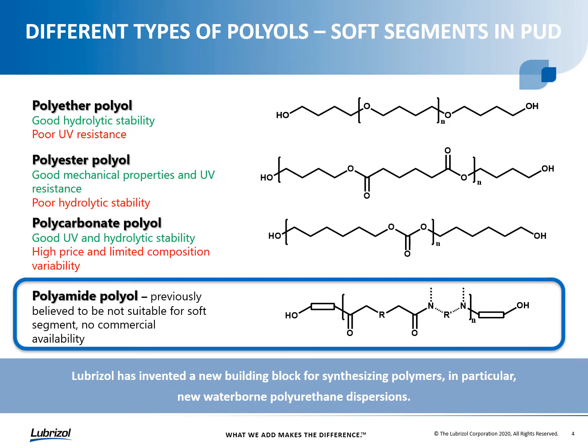So there are different types of polyols or soft segments that are used in making PUDs that are selected based ultimately on the various end-use performance requirements and properties you're trying to build into the resin. The main categories of polyols are the polyethers, polyesters, and polycarbonates. And you can see here they each have their own sets of inherent strengths and weaknesses. The polyethers tend to have good hydrolytic stability, but poor UV resistance, so you wouldn't really want to use them in outdoor applications. The polyester polyols are your general workhorse category of polyol, and they have good mechanical properties, good UV resistance, but they have poor hydrolytic stability, so they don't hold up well in the presence of water. And then the third category are the polycarbonate polyols, and these have good UV resistance, good hydrolytic stability,